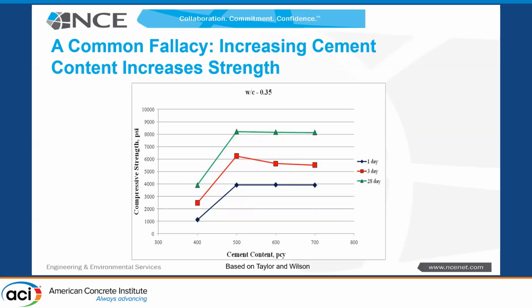That is not true. Now, it can give you higher early strength because the heat of hydration will kick it off a little bit more. And that is of value in construction, right? If you're a contractor, you want to be able to strip forms as early as you can. Or when you're slipping a pavement, sometimes you want to be able to use that for an access road. But on airports, sometimes you're not under the same time constraints, so you have a little bit more time. But the bottom line is this is some work that Peter did with one of his grad students that showed that at different days, once you get beyond a certain cement content, there's no change.